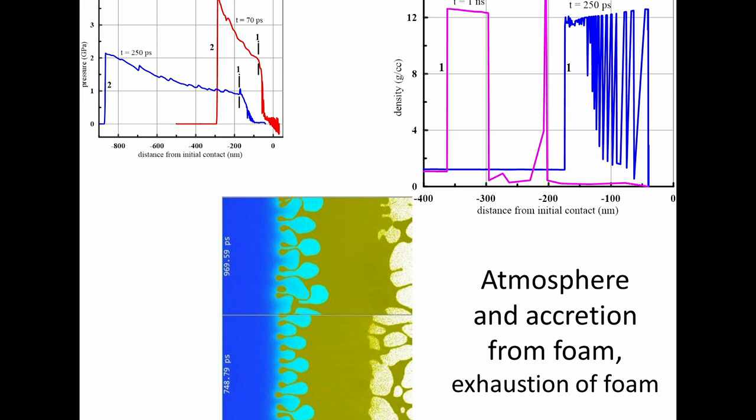And these fragments of the foam fall down, therefore the atmosphere becomes thicker, and also the water is heated. The blue color means this is bulk water, deep blue, and this is light blue water which is heated due to molecular heat conduction in water. It is small, two orders of magnitude smaller than in metal, but it is enough to heat water near the contact.